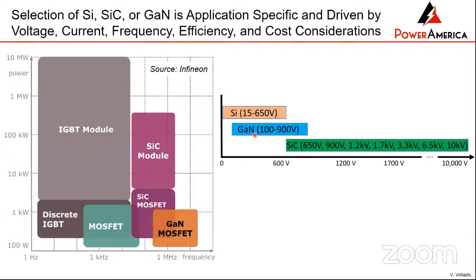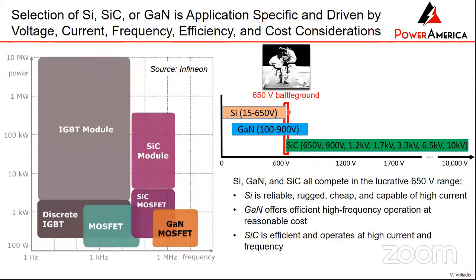If you look at power devices under 650 volts, silicon is very, very strong, and GaN is also competing very effectively in that area. If you look at devices that are 900 volts and beyond, then it's really silicon carbide, where devices have been shown at 1200 volts, 1700 volts, all the way up to 10,000 volts. And the big area of competition, the big battleground, is right here at 600, 650 volts. The 600 volt area has a very large number of applications, so it has a lot of volume, and silicon is very effective because it's very cheap. GaN can also be made well at 600 volts. It's a good competitor, and of course silicon carbide is also very capable at 600 volts.